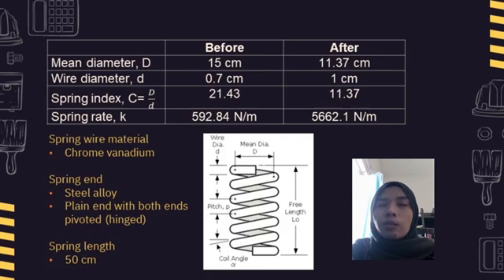From this table, we can see the before and after of the spring properties. For the mean diameter of the spring, before we use 15 centimeter. After we use 11.37 centimeter. Before modification, for wire diameter we use 0.7 centimeter. After modification, we use 1 centimeter. So from the diameter, we calculated the spring index. Before it is 21.43, so it is over the range. Well, after modify, it is in the range, which is 11.37.